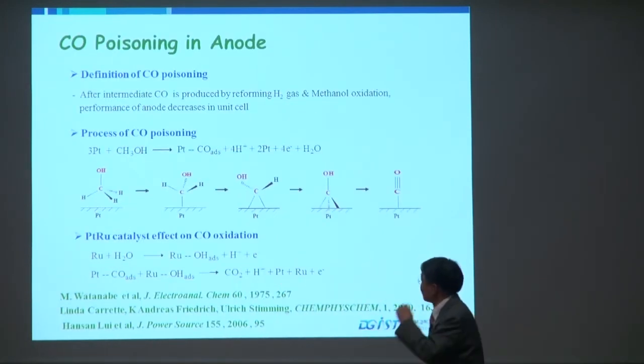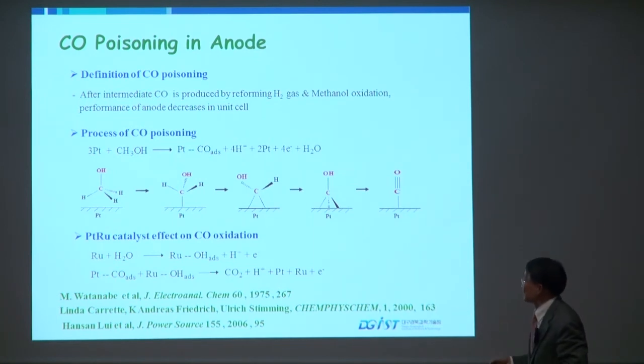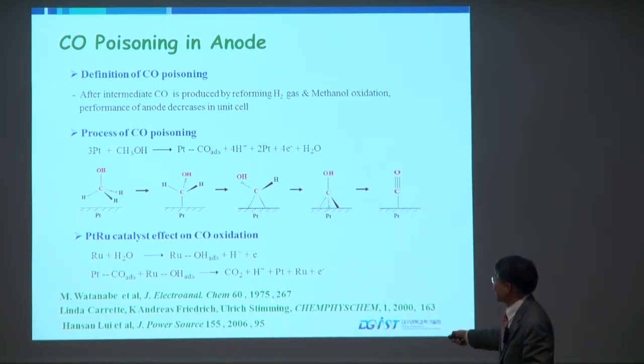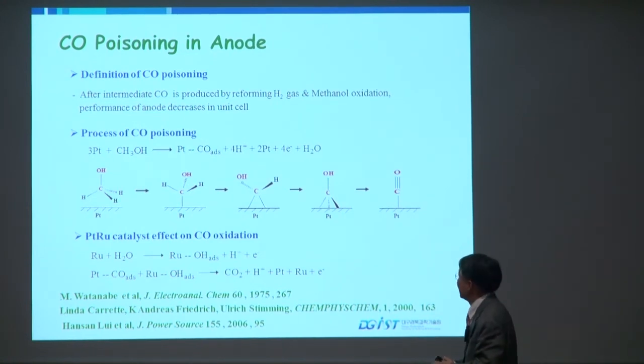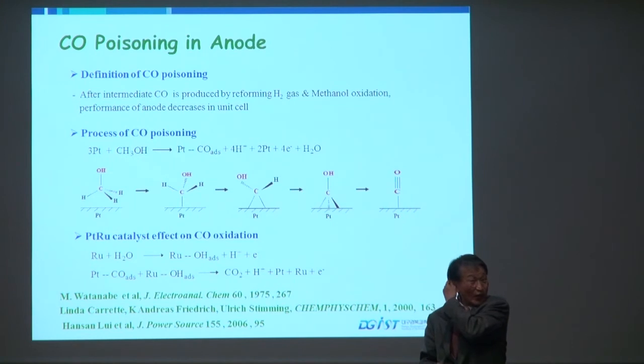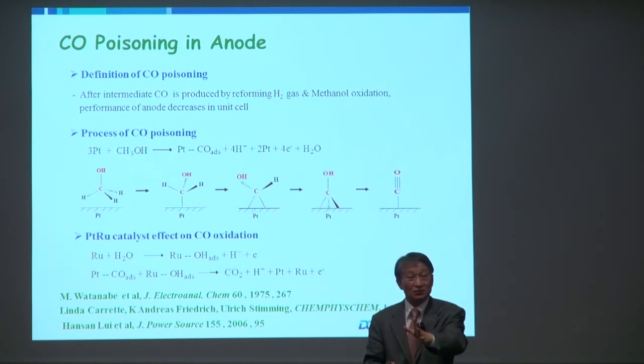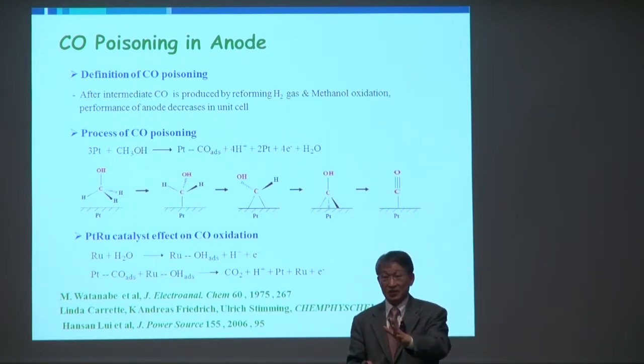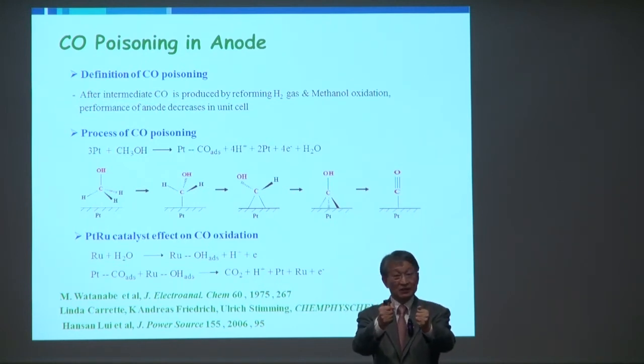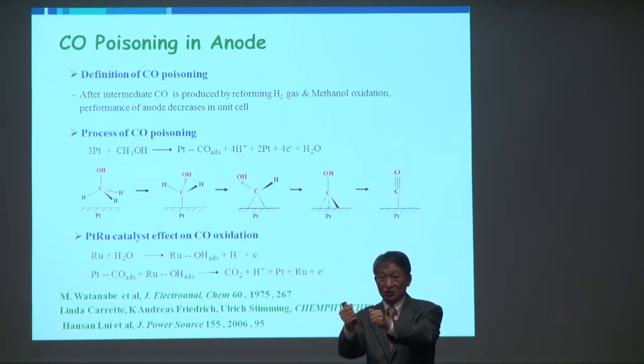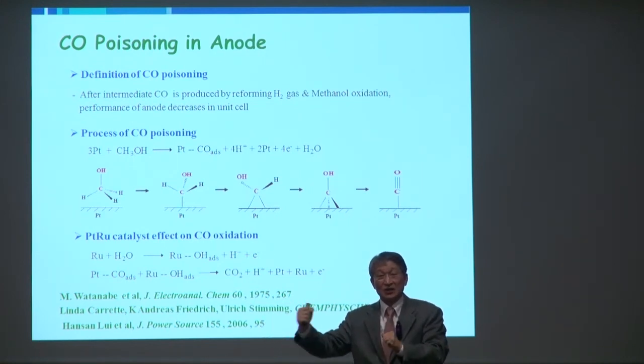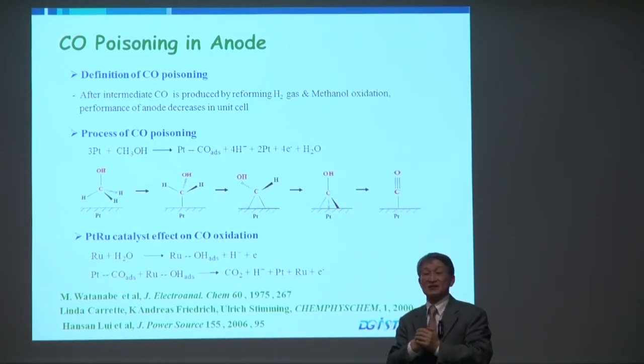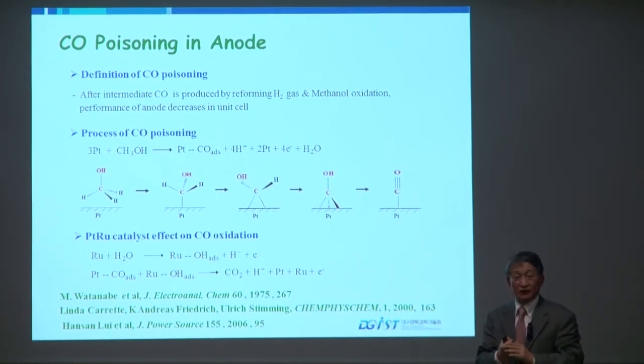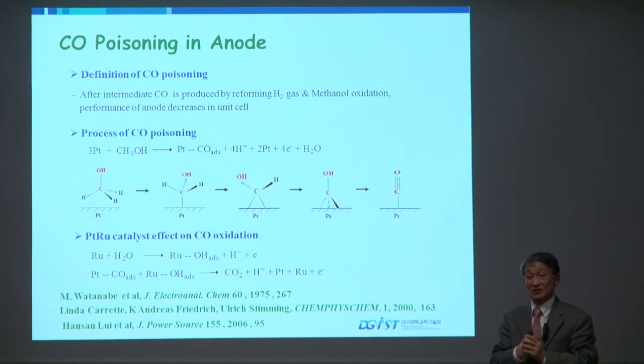This is due to the bifunctional mechanism proposed many years back by Professor Watanabe at Yamanashi University. So when we have an electrochemical deposition or co-deposition of platinum and ruthenium, perhaps the proximity between these two atomic catalysts turns out to be better than the commercial catalysts. So that bifunctional mechanism works favorably on electrochemically deposited surfaces.